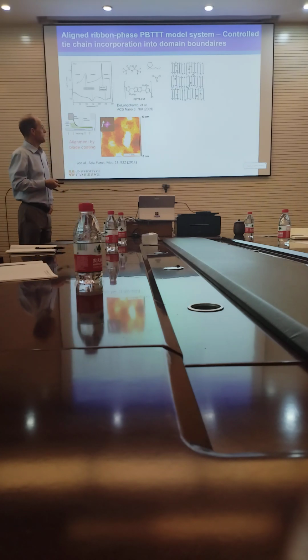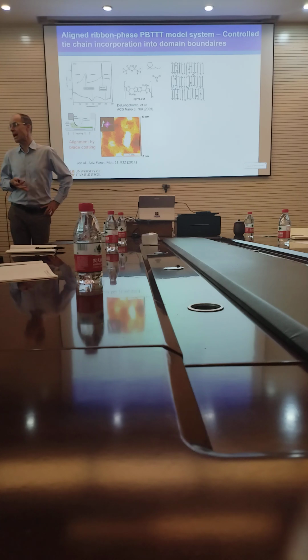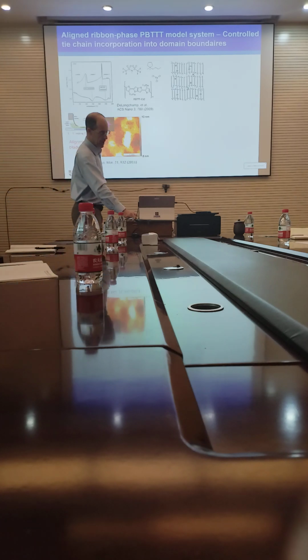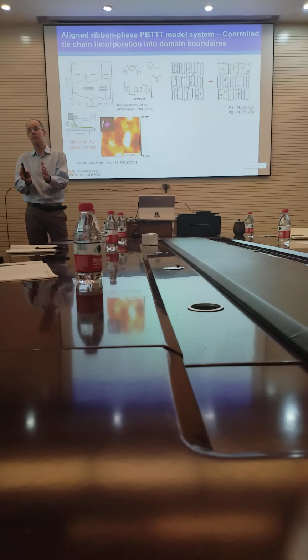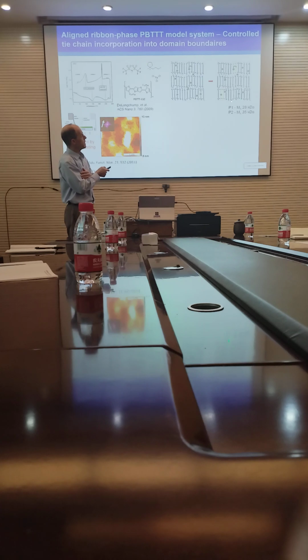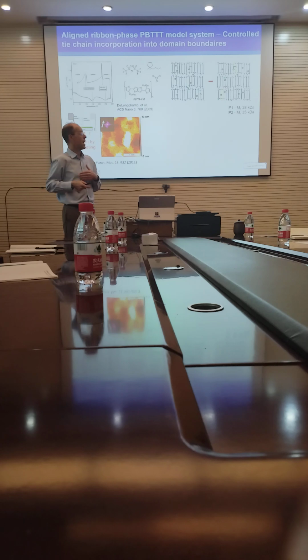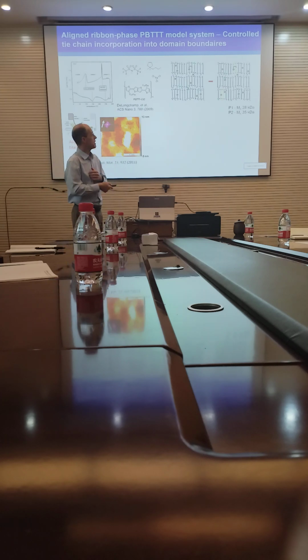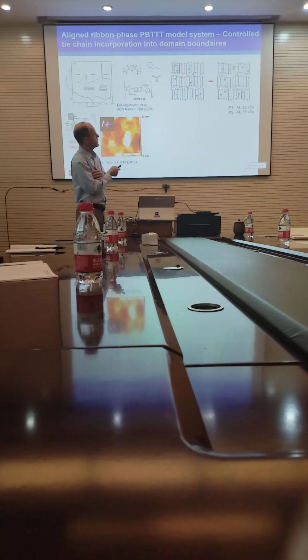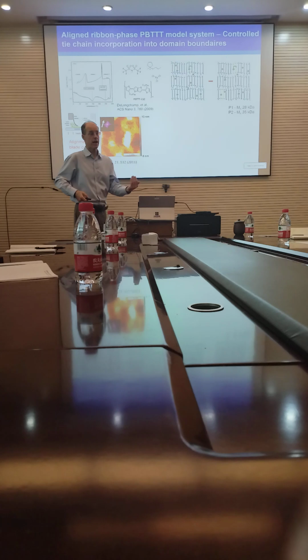So we thought, in order to improve the conductivity, let's try to incorporate some tie chains into this system. And the simple way you can do that is to essentially make a blend, where you make a film with a particular molecular weight, and then you add a small percentage of a polymer that has a slightly higher molecular weight. And then what we were hoping is that we would incorporate these red tie chains, the longer molecular weight chains. If we're lucky, they would get incorporated in this way here, where they form tie chains between those crystalline domains. And we were hoping that this would increase the electrical conductivity, because then the charges can move across one of those domain boundaries without having to hop onto another chain. They can move on one chain into the next crystalline domain, and then in the next crystalline domain they can hop onto the next chain.